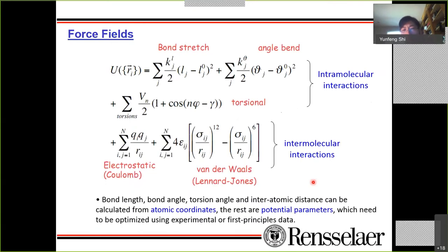So here is an example of a force field. You can see here, this is bond stretching, right? Just by looking at the formula, you kind of know what this term means. So here is your length. This is basically looping over all the pairs. Lj is the bond length of the pair, minus Lj0, that is your target or equilibrium bond length, squared, times k over 2. That is your elastic energy, your spring energy, half k L squared, right? So an elastic spring term to stabilize some kind of biomolecules or something like that.